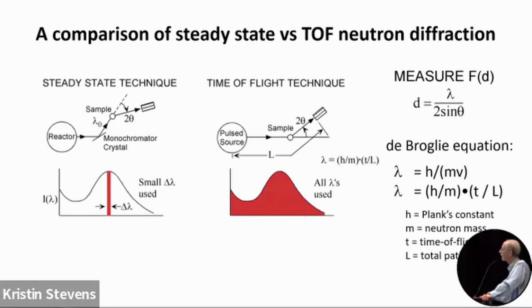And with the time of flight technique, here's the source and the sample, and the source is pulsed, so we can measure wavelength by measuring the time of flight with a fixed path length using the de Broglie equation shown here. And so with time of flight, we can fix the angle here, so it's a fixed 2 theta angle, and we're varying wavelength in the Bragg equation.